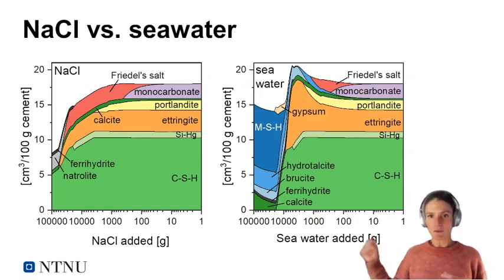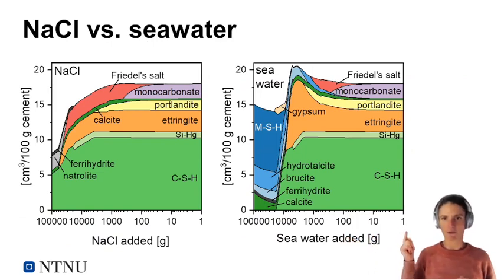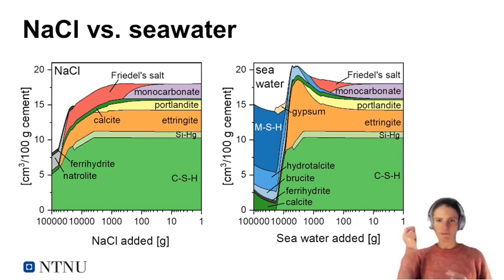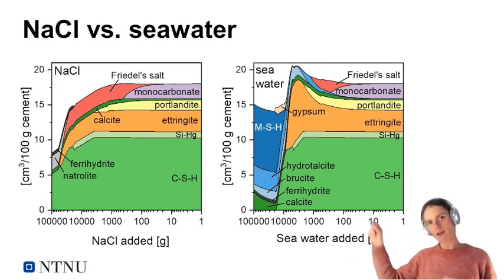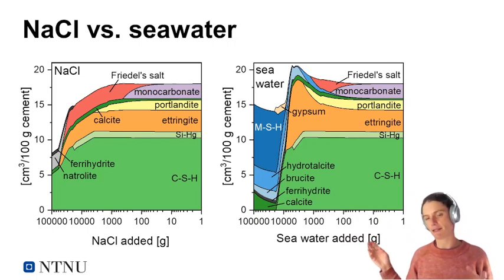So the figure at the left is for sodium chloride solution, and you have to read these figures as follows. Where we have 1 on the horizontal axis, that's where we have a very small addition of the exposure solution to a hydrated cement paste. So let's start with the sodium chloride. If you look at 1 and above there, you see the hydrated assemblage of a hydrated cement paste with very little sodium chloride added.